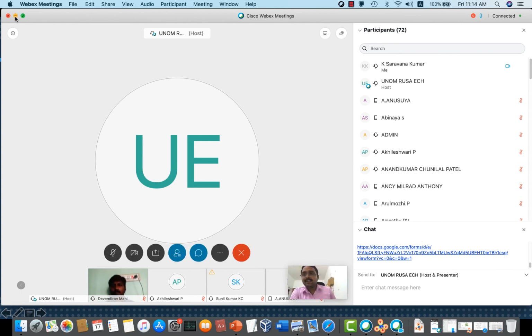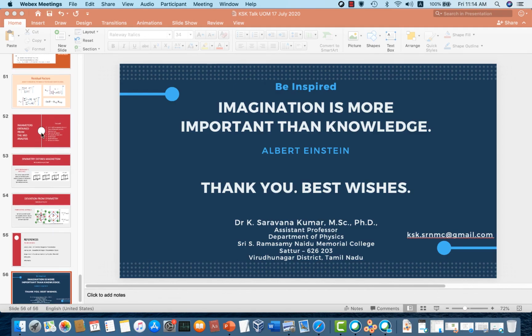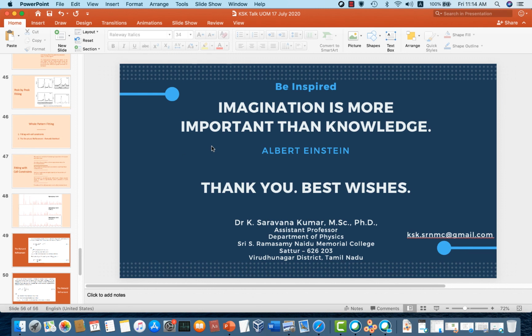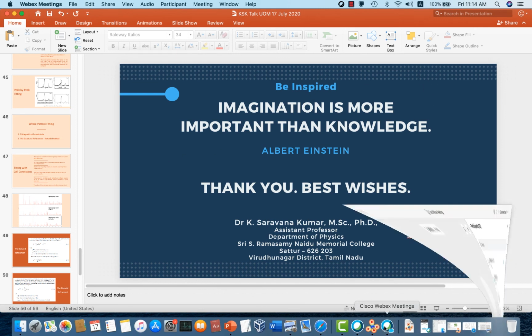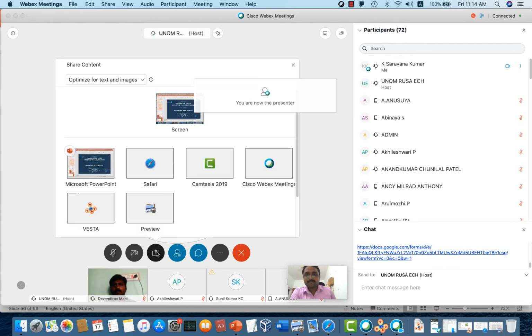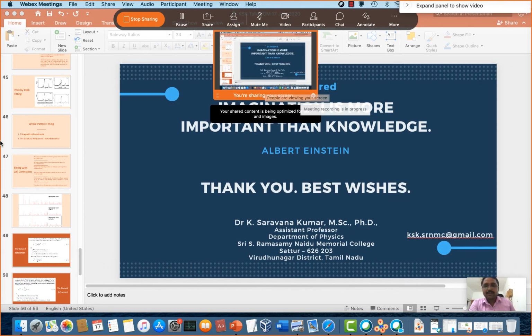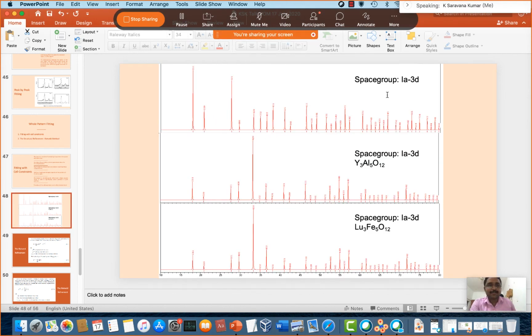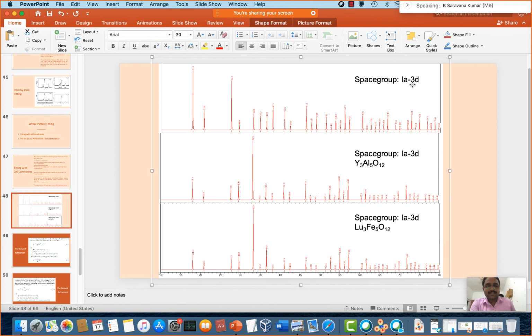Yes, I can tell you on that. You can see here. Can you see my screen, sir? In this particular slide, you can see the space group, right? According to the space group of your material, if there is a peak at 22, you can use that as your sample peak, no problem. If it is not allowed, then it can be due to some other reason. If your material has a particular space group and that space group allows that 22 degree peak, then it can be included as your sample's peak, not a problem.